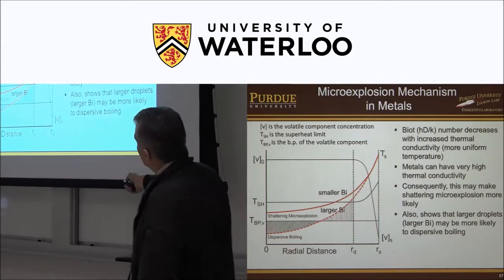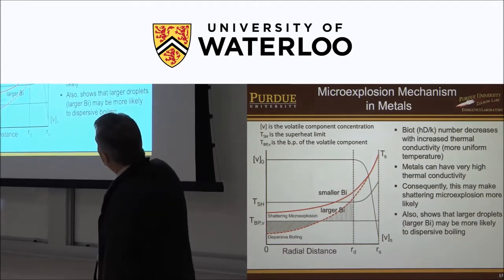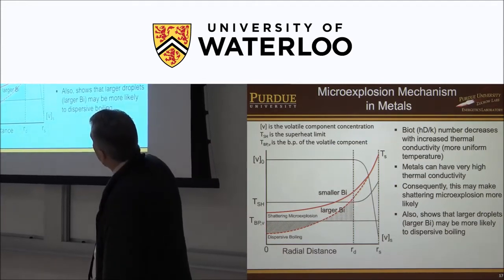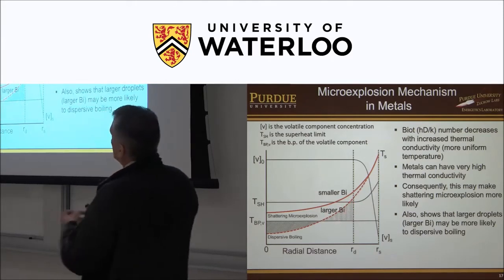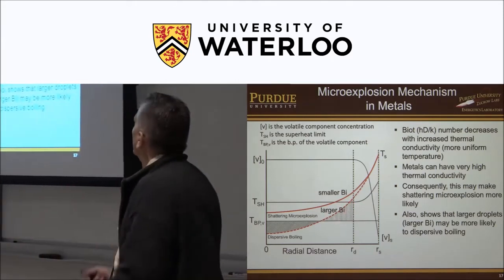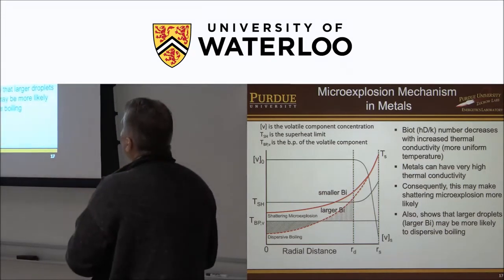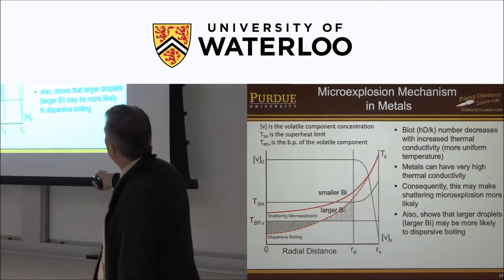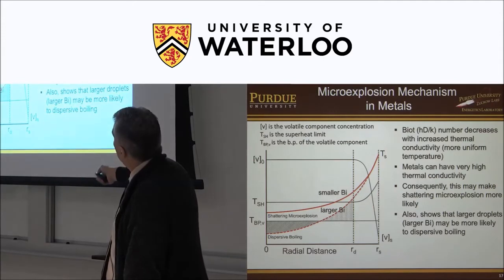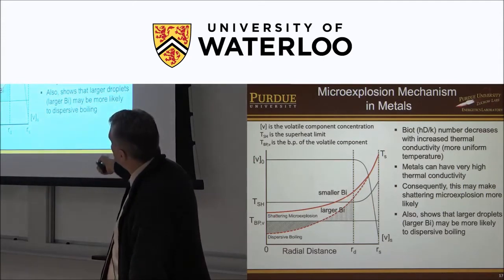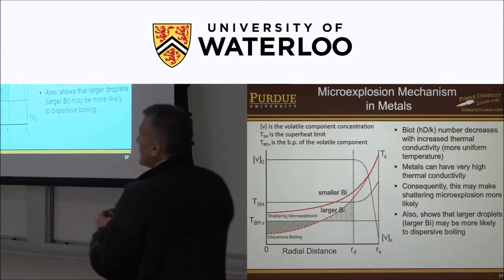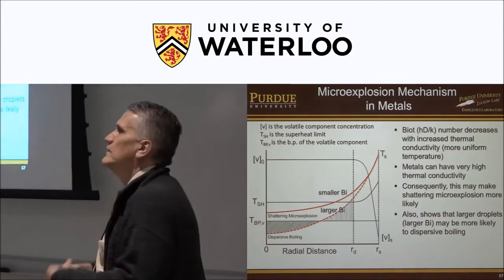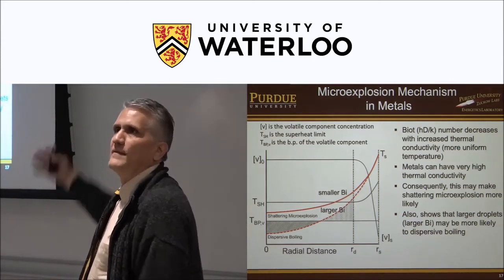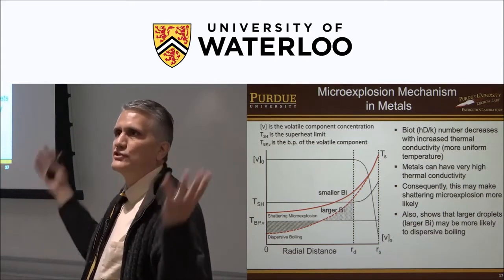And so for dispersive boiling, you may have part of that droplet above the boiling point of the volatile component. That's what this line is. When that exceeds the superheat limit, this region will flash to gas, but not the whole droplet, and you'll have this dispersive boiling, kind of a volcanic type of boiling. In the other case, with a shattering microexplosion, you could have pretty much the entire core superheated. You exceed that superheat limit, and that whole core flashes to gas and shatters the droplet.